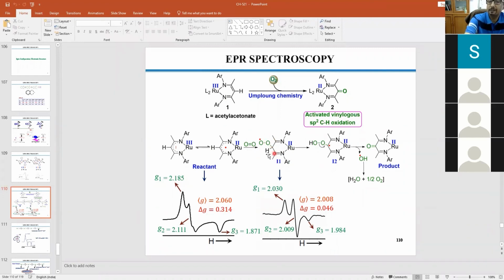And the superoxide intermediate could also be easily characterized by the radical-based EPR if you look at the g and delta g. But slight anisotropy is happening. This is the expanded scale along the x-axis. So it looks like this one, but it is not so. It is basically a radical signal which has been expanded for your understanding that this unpaired electron is partly diffused onto the metal. And as a result, you can think about another type of resonating form over here, and that is how the anisotropic feature appears.